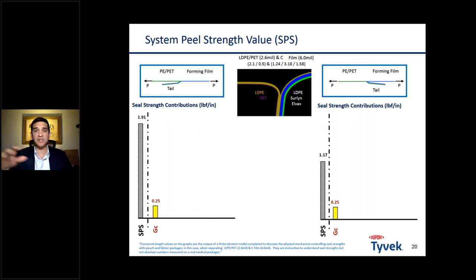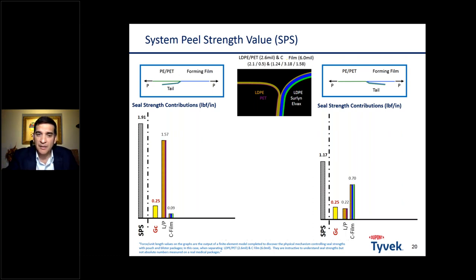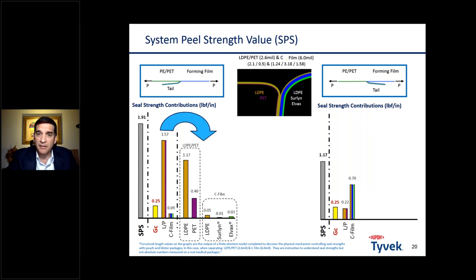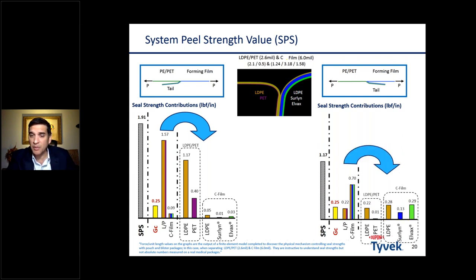That first G sub C is the same. It's going to be the same for both materials. Pulling it apart will be the same. But when you look on the left-hand side, you can see the polyester poly. And when we further break it down, you can see the polyethylene is actually contributing 1.17 of that 1.91, and then the polyester is also contributing, and the C film is not. And if we look on the right-hand side, the contribution from the polyethylene is 0.22 when we do it the other way.